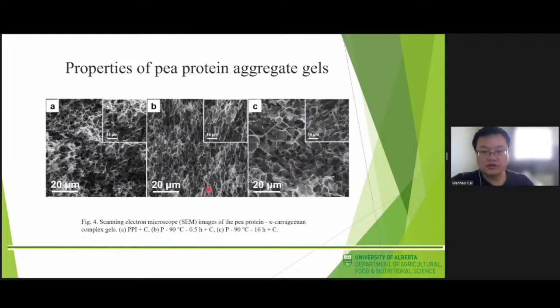The gel microstructure showed a well cross-linked network in SEM imaging, likely due to the presence of κ-carrageenan that could form a polymer-like network based on associated double helices. Such a pre-network could provide a sort of scaffold for more uniform growth of pea protein aggregates into a densely cross-linked gel network. It was noticed that a more uniform network with a smaller pore size was observed for the gel prepared from the half-an-hour aggregate sample with κ-carrageenan when compared to the gel formed from the pea protein isolate of 16 hours aggregate sample.